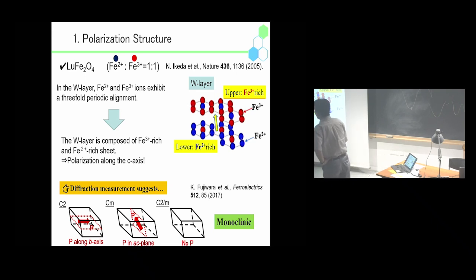But after his proposal, for more than 14 years, there was much controversy. One of the reasons is that there were scarce good single crystals at the time. The second reason is that neutron diffraction measurements couldn't determine the crystal symmetry, let alone the polarization. The neutron diffraction measurements suggested three candidates: C2, Cm, and C2/m, polar, polar, and nonpolar. So after this proposal, for more than 14 years, there were many struggles.